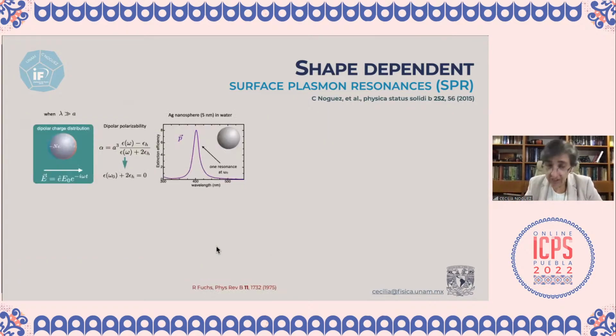Like I said, for example, when the particle is very small as compared with the wavelength of the incident light, the response of the nanoparticle, the extinction efficiency that the detectors will obtain, depends on the dipolar polarizability of the nanoparticle. Okay, and this dipolar polarizability for a sphere, just for a sphere, depends on the sphere radius, and also on this expression of the polarizability that has to do with the dielectric function of the nanoparticle and where the nanoparticle is.